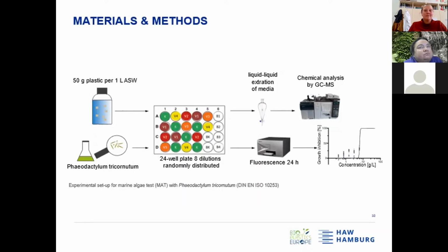Afterwards, the algae were added to the plate. And for every concentration, one well was only filled with the media and without algae, because of the extraction of the media. So these wells were extracted by liquid-liquid extraction with hexane and afterwards analyzed by GCMS. And the plates were analyzed with a Tecan reader.